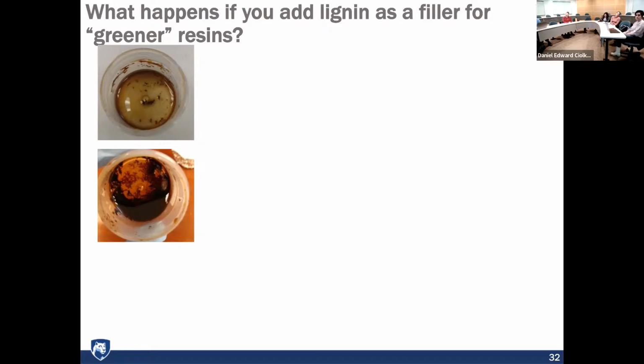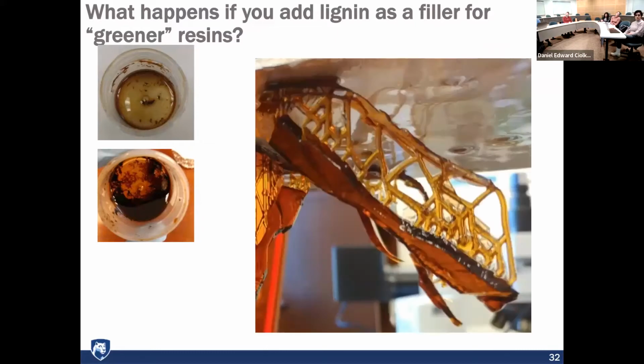That's bad. We don't want the chunks, because when you try to print with the chunky stuff, you get these specimens that almost look like they're melting off the build platform. So this is the build platform. Imagine the resin tank is down here and the object comes up this way, and they look kind of gooey and not so good. And this is because you have this heterogeneous resin. You want a nice, smooth, homogeneous material if you want to get homogeneous objects printed.